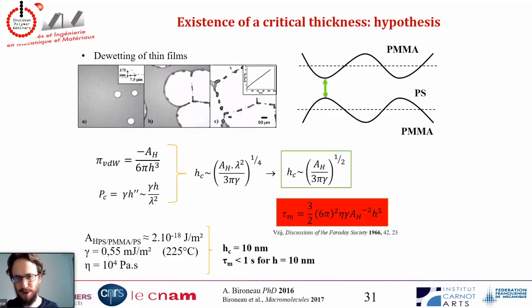So I'm just going to conclude with what we think it is. To explain this critical thickness hypothesis, what we have is similar to the problem of the dewetting of thin polymer films. Here I'm looking from the top at a polymer thin film, 15 nanometers or so, on top of a substrate. So it's only one layer, not a multi-layer system. But if you put this 15 nanometer layer on top of a substrate with which it has no affinity, and you heat it above the Tg of the glassy polymer, it will spontaneously create some holes, and these holes will grow, and the material that was in the film will segregate in the rim around the hole, and at the end it will coalesce and form this kind of droplets.